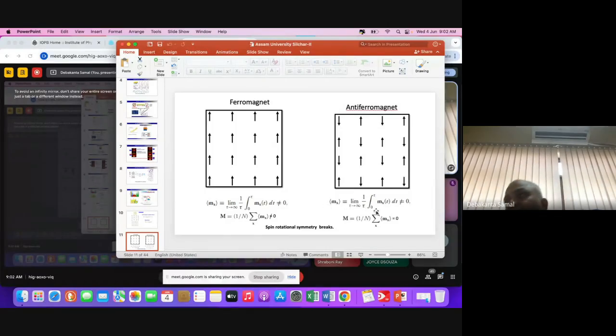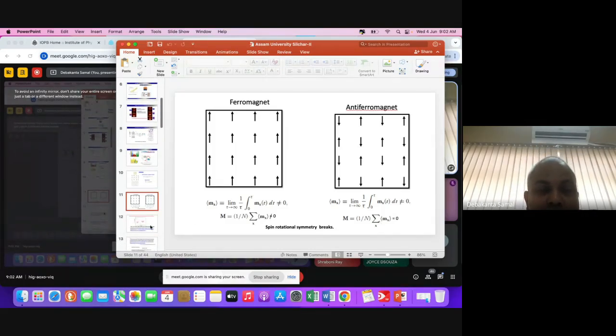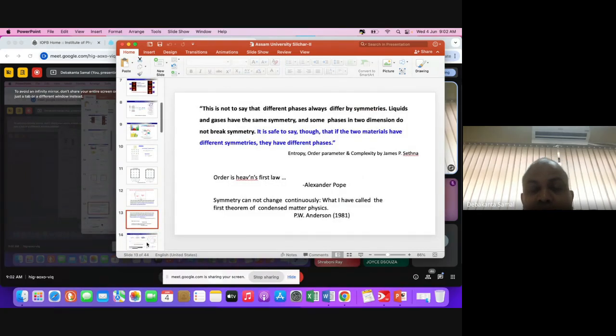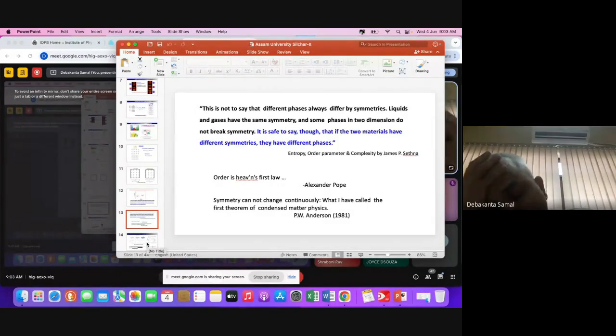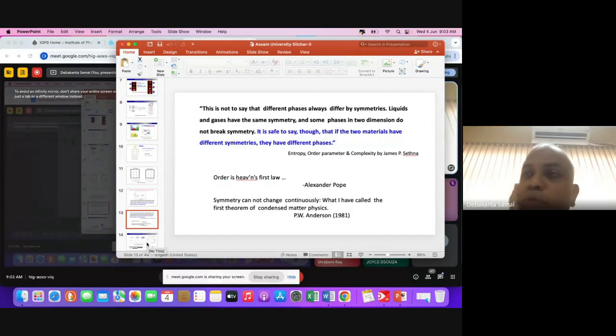But for an antiferromagnet, similar to a ferromagnet, the time average magnetic moment at a particular site is not equal to zero. But the overall magnetization is zero because it is an antiferromagnet. You have an equal number of up spins and down spins. I told you that to understand this paramagnetic to ferromagnetic phase transition, you need to consider symmetry breaking, where paramagnetic is a disordered phase and ferromagnetic is an ordered phase, and the theorem tells that if there is a phase transition, in most cases there will be a symmetry breaking. For example, from paramagnet to ferromagnet, the spin rotational symmetry breaks. Similarly, when you go from liquid to ice, some symmetry must be breaking there.